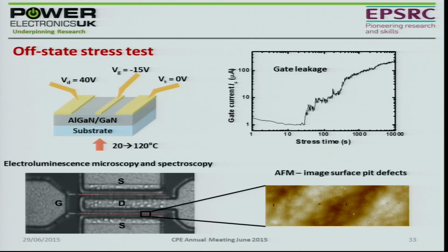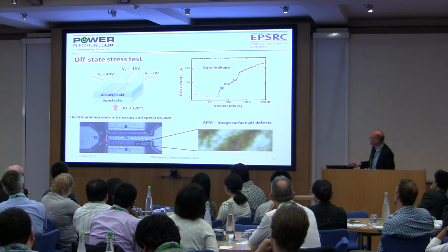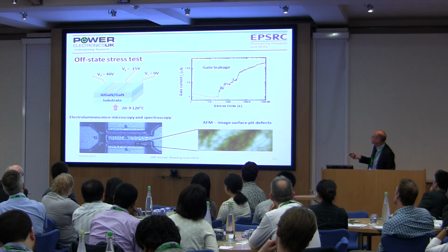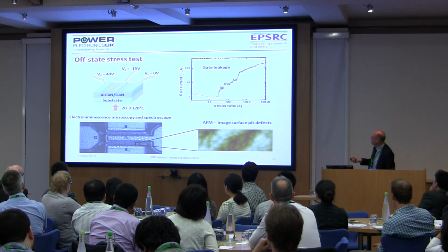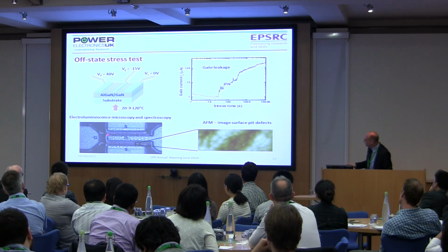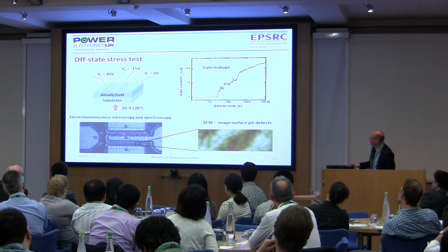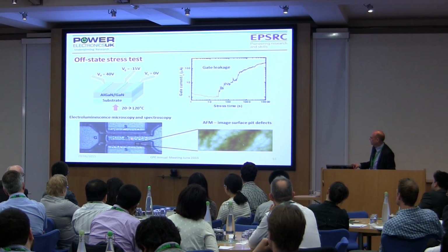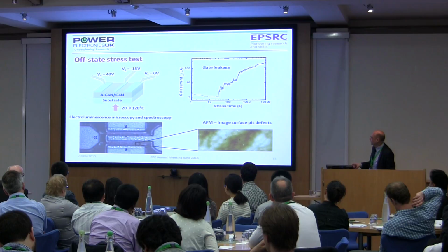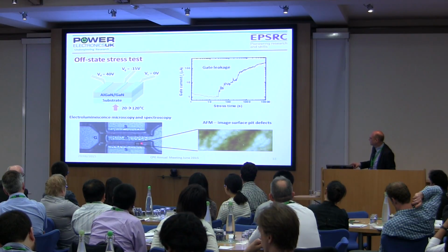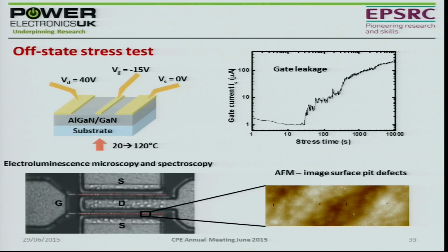That's an AFM image looking along this edge. Now, what they found is that with time, as you stress this device, the leakage current through the gate increases. It increases exponentially. And that's due to defects forming. And you can see these little red dots here. They are pointing out defects on these gate fingers as they grow with time. And this is a zoom in of that. You can see these little pits that occur along the fingers. And they multiply with time. You get more of them.